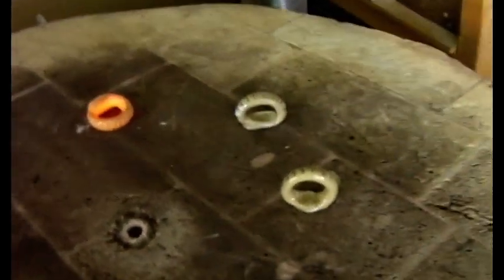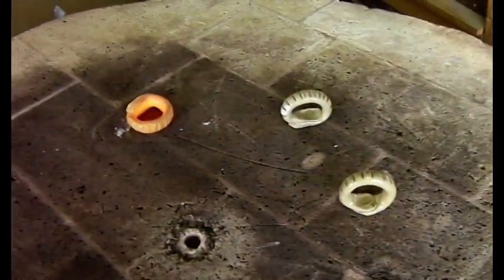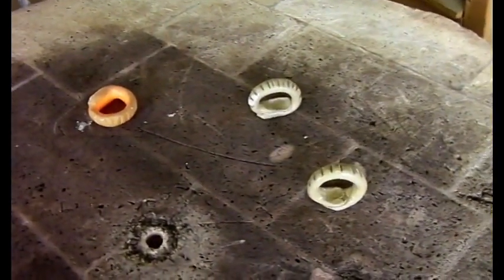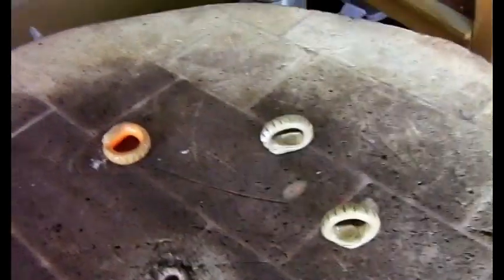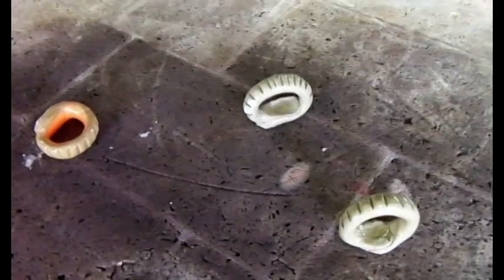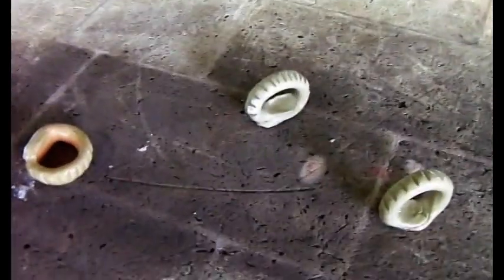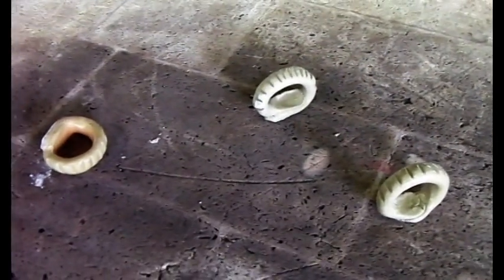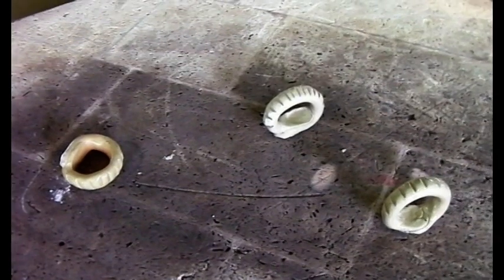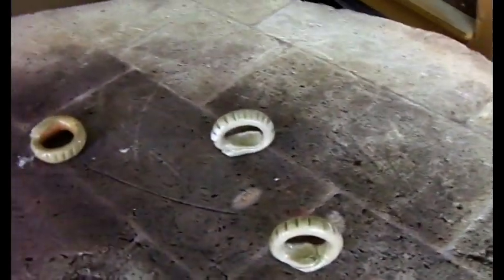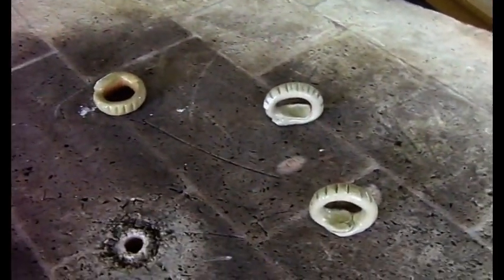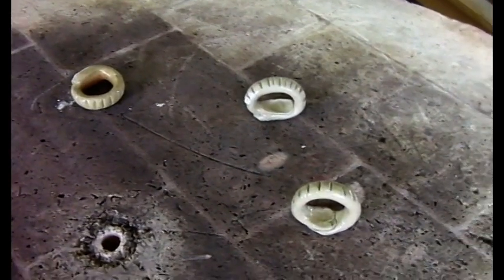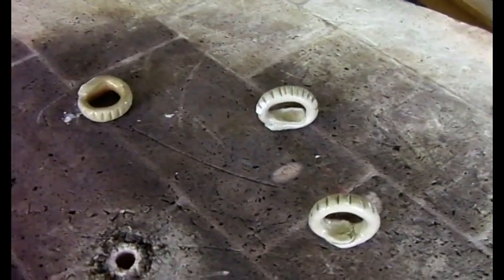So these are test rings for our salt firing. We pull these out after each time we put rock salt in the kiln. Over time, the rings, after each one, will get heavier glaze on them. We'll get a shine, so we'll know if we need to add more salt or if the coverage of the salt is good and we can stop. So these are just little test draw rings, they're called. Right now they're probably still 2,000 degrees, so we can't touch them.